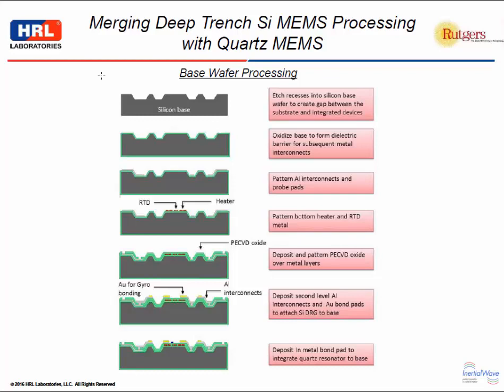We start with a silicon 100 base wafer. That was typical for the gyro processing. We didn't do a lot of modifications to the silicon base process. We first etch pillars in the silicon base for standoffs for eventually bonding the silicon gyro. We oxidize the surface and we do a first level aluminum interconnect. The interconnects for the gyro are quite complicated, and they had all previously been done with aluminum. We then added some platinum RTD and heater elements to the center. This is the center pillar. And then we applied a PECVD oxide layer for isolation between the first level and the second level metal. And then we applied second level aluminum interconnects, bringing the interconnects out to the edge of the die.